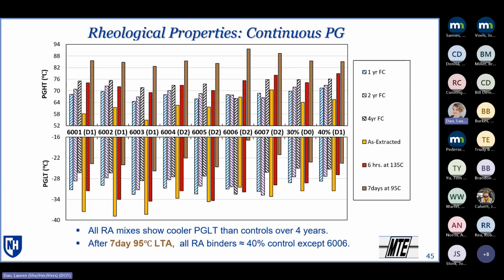So looking at the low temperature, you can see for all of the RA mixes, after 4 years of aging, they're still showing a lower continuous PG than the controls over 4 years. So that in-place material is still showing performance that we expect over the 4 years. But once you get to that longer aging level, the 7 days at 95, they're getting close to that control material. So they're losing that effectiveness for the low temperature PG at the longer time.